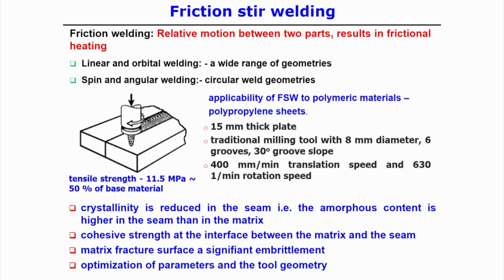So, that means exactly at the seam joint the crystallinity is reduced. That may be one reason that we are getting a very small joint strength as compared to the base material. Then cohesive strength at the interface between the matrix and the seam, this is another characteristic behavior we can find out.